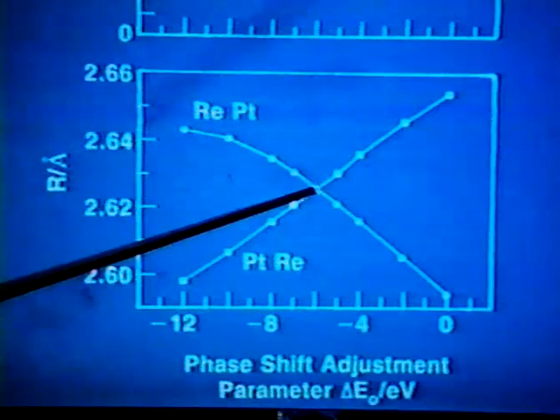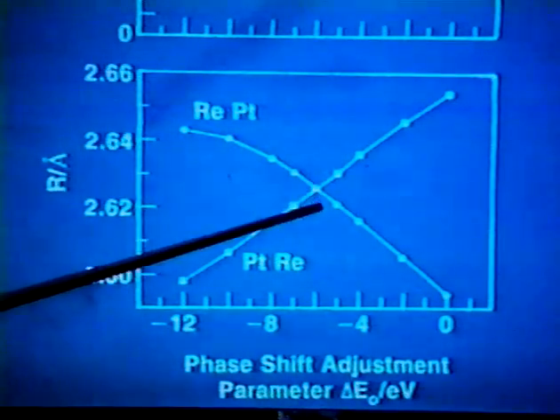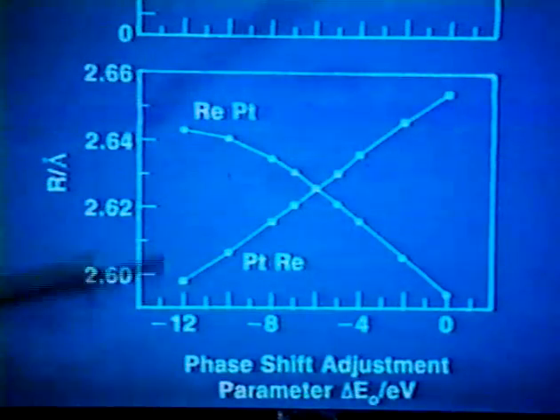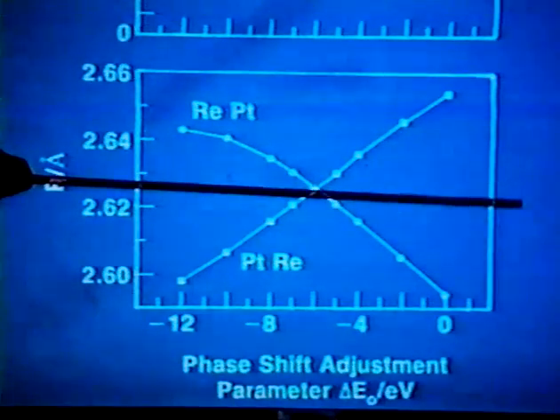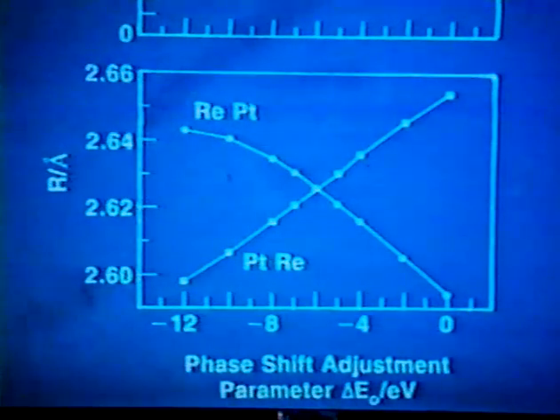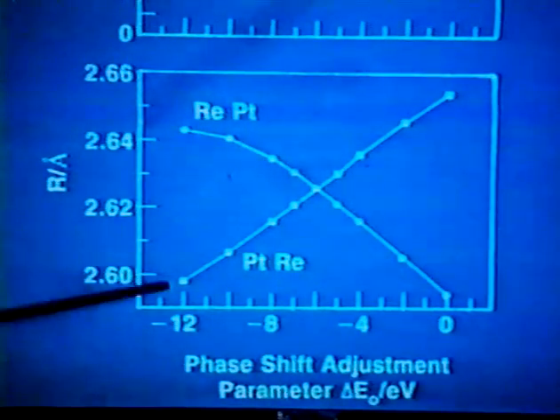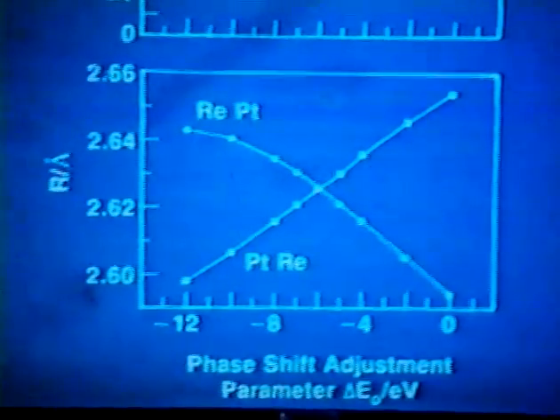But we used this criterion, that the Re-Pt distance equals the Pt-Re distance, to fix any other physical parameters that we determined. So this gave us the platinum-rhenium distance. It was here 2.63 or something like that. And it also fixed the composition of the platinum and rhenium coordination shells. Now this was a good thing to do. There are other variables that we could have fixed as well, but for practical purposes, this was an enormous amount of work already. And if you try to put constraints on other variables as well, the amount of work increases so rapidly that soon you just can't cope with it. So this was the only such criterion we formally enforced. Next slide, please.